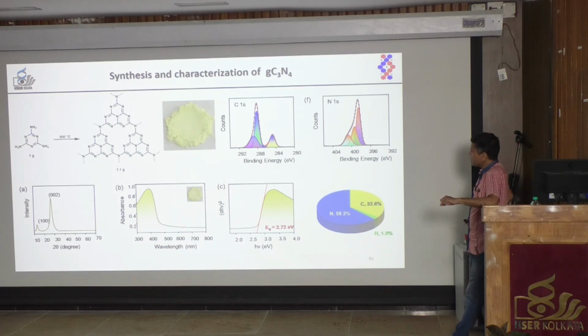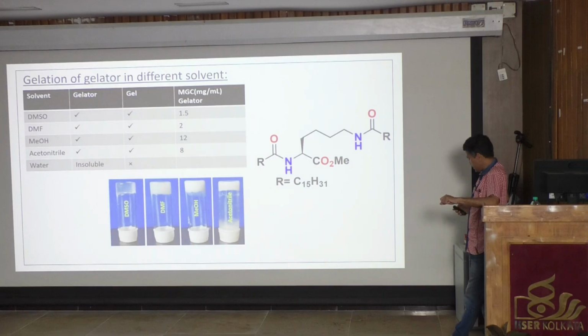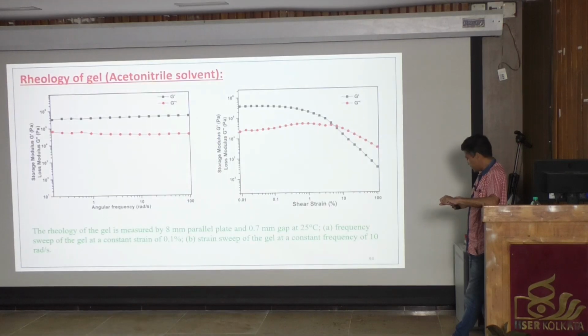So we made that photocatalyst. We studied the state of the photocatalyst with all the spectroscopic techniques. Then we made this gelator, again a different kind. Similarly, this gelator does not have any aromatic system, so it cannot absorb light. It forms gel in different solvents like DMSO, DMF, methanol, and acetonitrile. We studied the gel with rheology, so the gel is very fine.